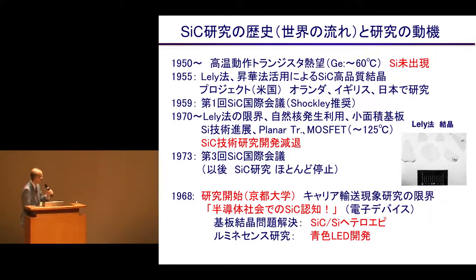And so the Lely method created high-quality crystal, but as you see in the right side photograph, the crystal is irregular and only thin film can be developed. So, which means that we could not create a device by this method. So the Lely method was not enough for a device.